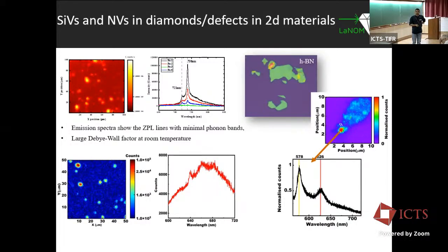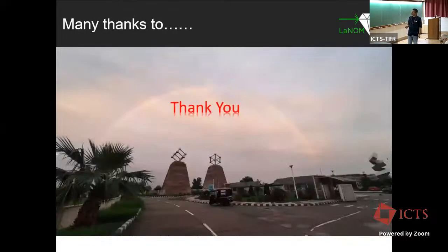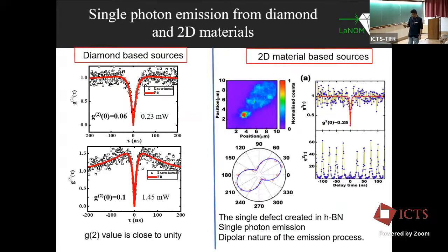I have one small question. You showed that g2 measurement. Why is it only about 0.4 or so? It is not my measurement, it is from the literature. But is there something better, close to 0? Yeah, I didn't show you because we have not done much analysis. This is our measurement, we got 0.1. It's not published, we have to do some more things. This is from a single NV center in diamond, not from nanodiamonds. And this is from a 2D material, we got 0.25 in hBN. Yeah, we can get it very close to 0.